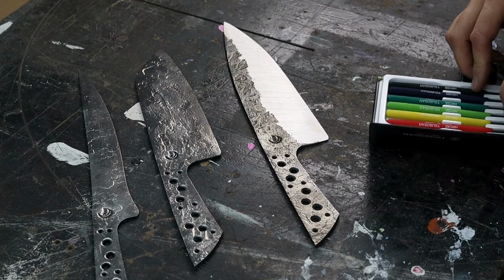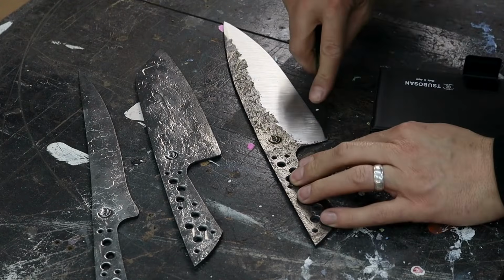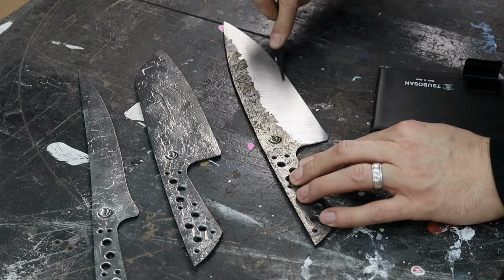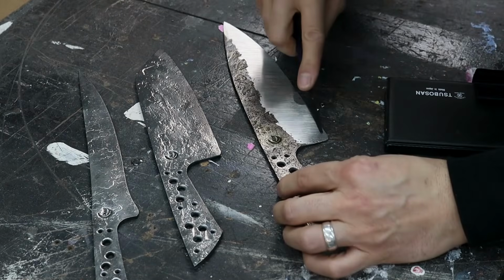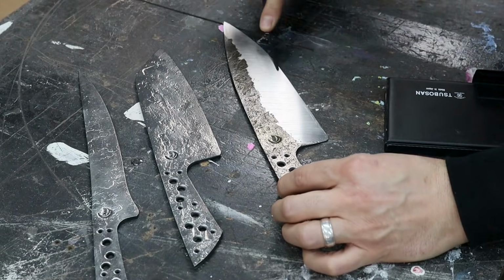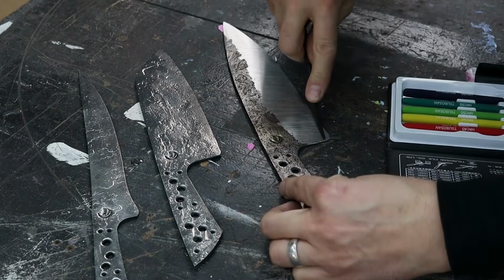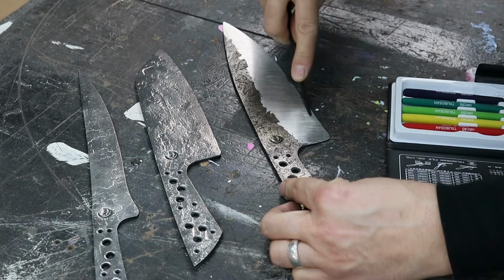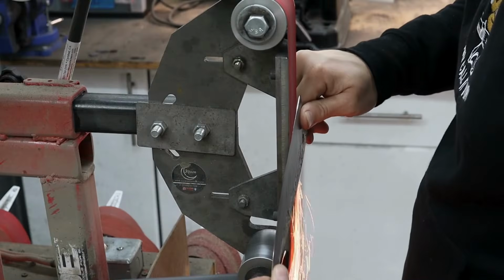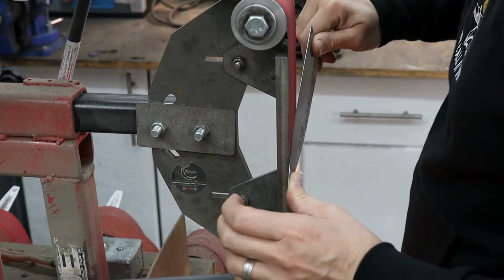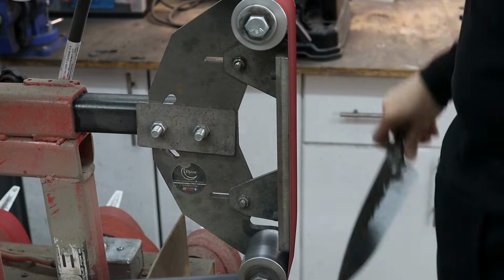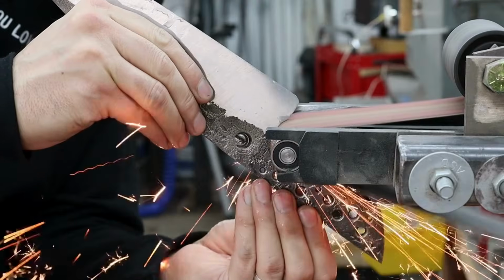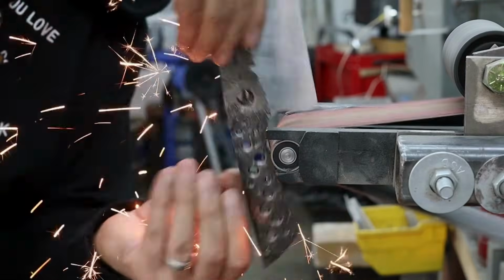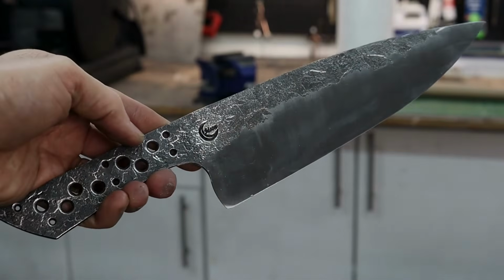Between the 120 grit and 220 grit belts, I like to test the edge for hardness with this set of Rockwell hardness files. I do this at this point because it ensures that I've ground through any decarb layer, and it's still pretty easy to smooth over any surface scratches from the files with the 220 grit belt. I would guess that both of the chef knives were around 61 Rockwell, and the fillet knife is around 58 or 59 Rockwell. The handles on the 2 chef knives felt slightly on the small side, so I ground in about an extra ½ inch.